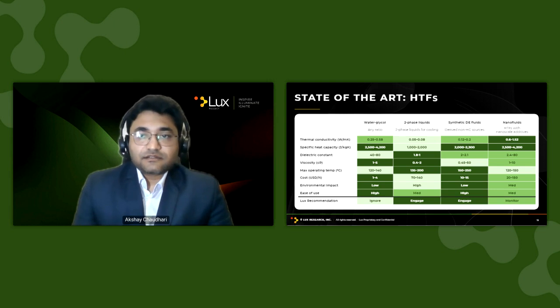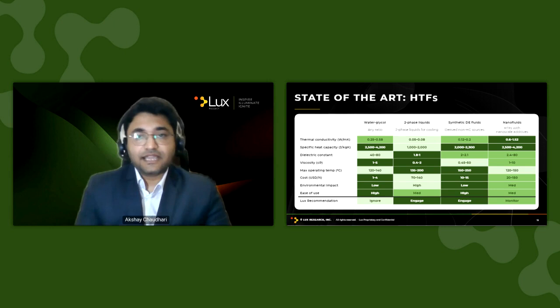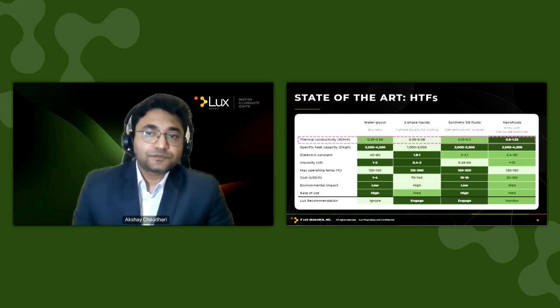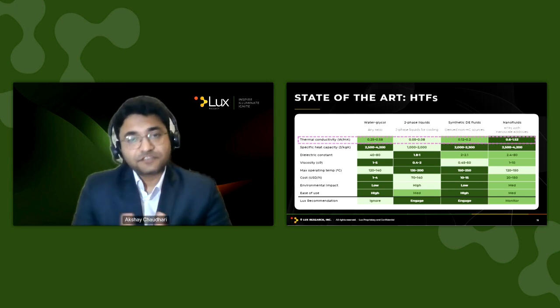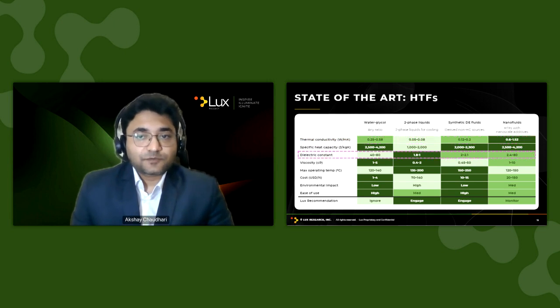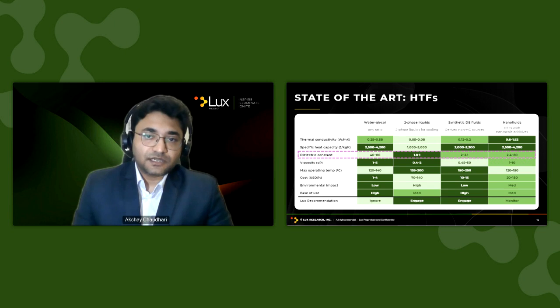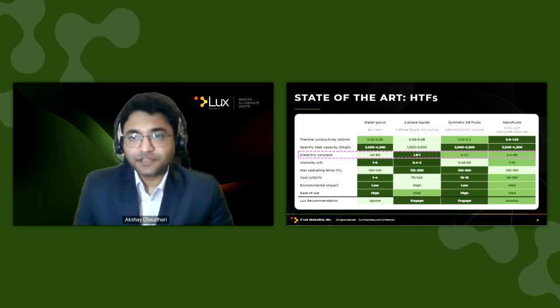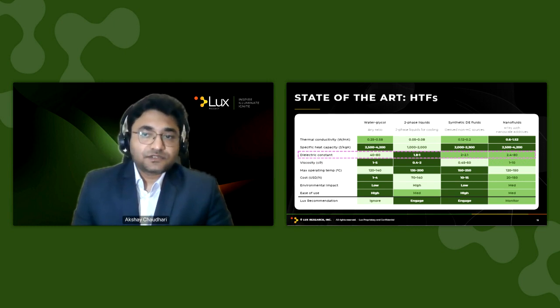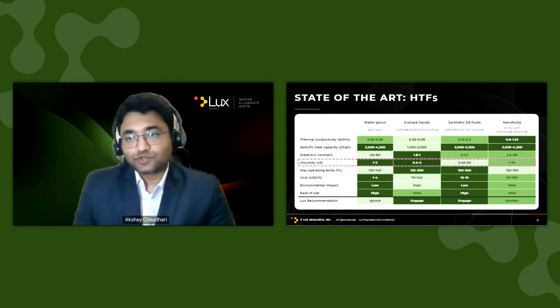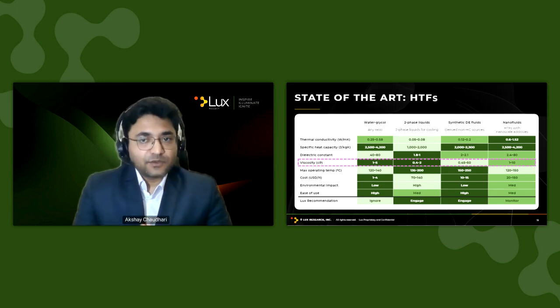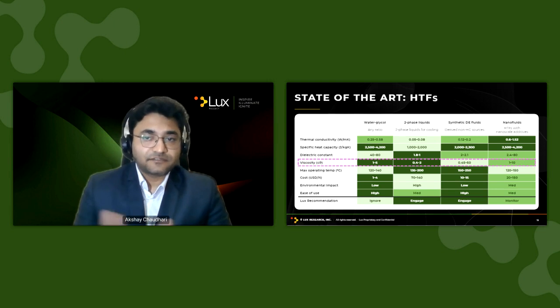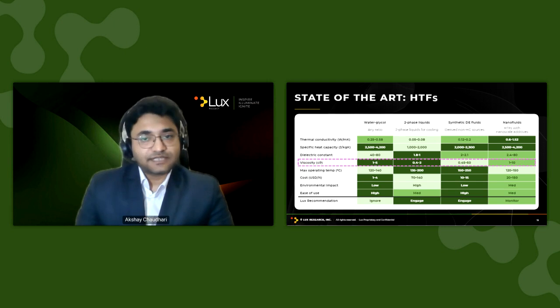As mentioned earlier, we are taking the same approach, with types across the top and the most critical key parameters down the side. If we look at the thermal conductivity, nanofluids are the winner due to the presence of ceramic nanoparticles, which enhance the heat transfer efficiency. When it comes to the dielectric properties, a lower dielectric constant is preferable to prevent electric interference, and among these, two-phase liquids offer significantly better dielectric properties. For viscosity, water glycol and two-phase liquids are well suited due to their low viscosities, whereas synthetic dielectric fluids have a very wide range, making only a few formulations suitable for this application.